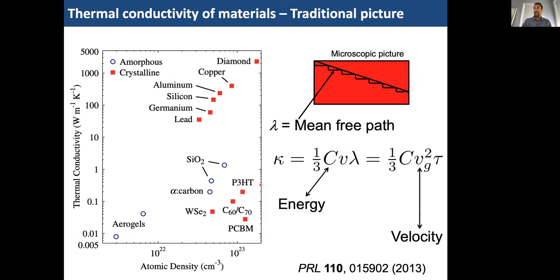But from a nanoscale perspective, there are different considerations that we need to have. So in the microscopic picture of thermal conductivity, we go back to that picture I had in the very first slide about the characteristic times and length scales of thermal conduction. And when you start to consider electrons and phonons and their individual interactions with each other, and how far a thermal carrier will travel before it scatters and loses energy or momentum with another particle or another aspect of the material, that's when you start to think about thermal conductivity in more of a nanoscopic picture.